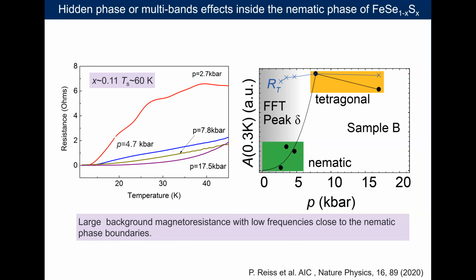Here I show some more data using pressure. So we did a similar experiment now with a single compound, but changing the pressure across the nematic endpoint. And similarly, as we approach the nematic endpoint in this green region, the magnetoresistance is extremely large and dominated by this low frequency. So this data is always reproducible. We always pick this up in the vicinity of the nematic phase transition. And also the amplitude of the high frequency quantum oscillation is sensitive to what happens. Its amplitude is very much suppressed. You see, it should be somewhere here, but it's very much suppressed. So there are likely other types of scattering processes occurring there, which explain all this behavior.